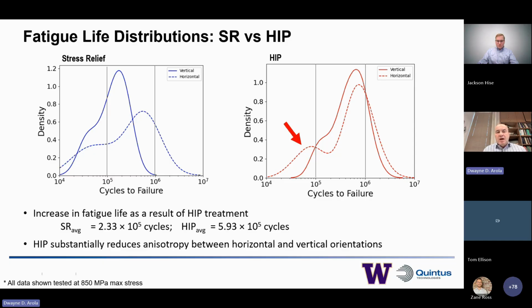So we find that the HIP process substantially reduces the anisotropy between the horizontal and vertical orientations, decreases the emphasis on trying to make sure that we get the orientation correct in a build to produce the highest quality metal for a specific orientation of cyclic stress. You can see that there's a small little bump here in that orientation for the horizontal samples. This is a result of those prior beta grains that are now oriented perpendicular to the axis of cyclic loading and their intersection with the free surface as a result of the build orientation. So small little bump here, but otherwise really great agreement between what we see in responses for those 2 orientations.